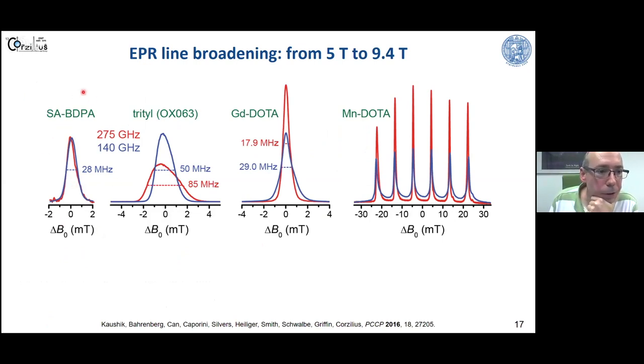And you can compare, for example, different radicals, BDPA and trityl. In BDPA, we have unresolved hyperfine interaction to protons, which is dominating the EPR line shape. So we have no increase in our absolute line width at higher magnetic field. So this stays exactly the same. In trityl, we have g anisotropy due to a mixture of excited electronic states. And this leads to an increase of this anisotropy on an absolute frequency scale at higher magnetic field, and also an increase in line width.